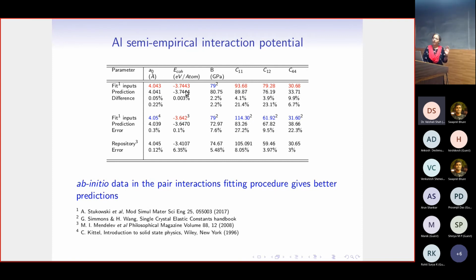So then we said, okay, we started with the ab initio data. Let us try the fitting procedure with the experimental data. So we take all the inputs from experiments, we fit the potential using the experimental data, and then we see if this generated pair potential would now give us a better agreement because we have taken it from experiment. So now the expectation is that it should agree with the experimental result.